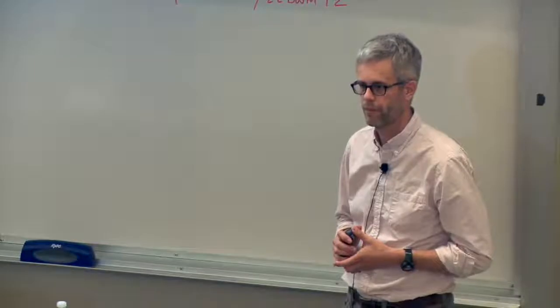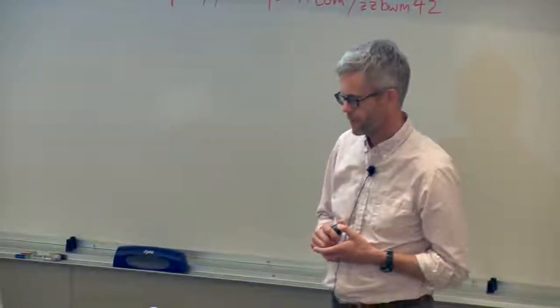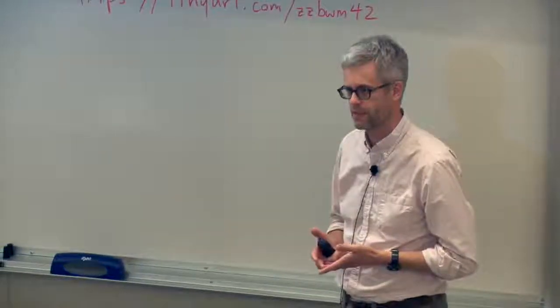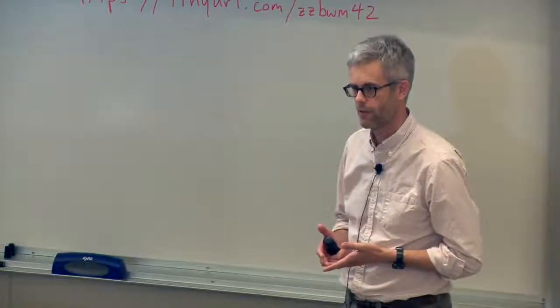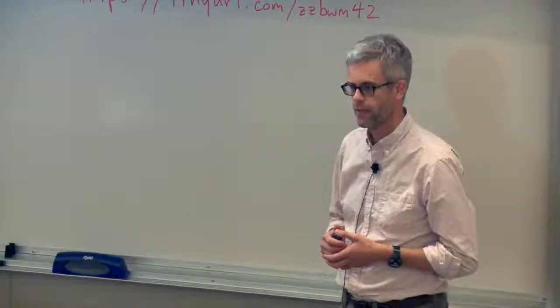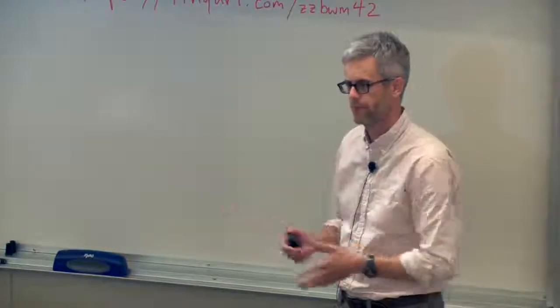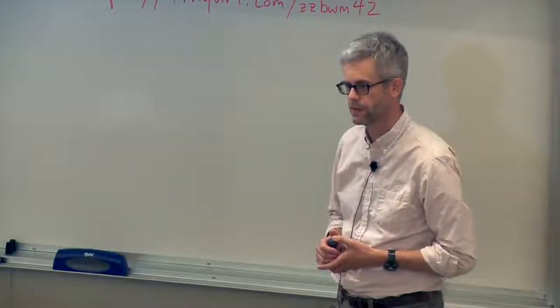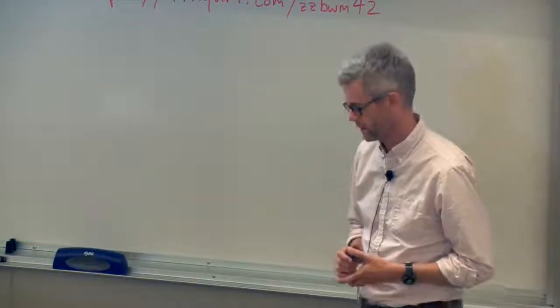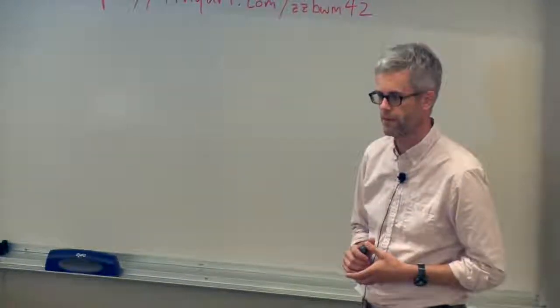What was silicon's efficiency again? Silicon right now, at 50 cents per watt, you would be getting 16% efficiency. At $1 per watt now, you could be up at 21 or 22. And we project all those efficiencies to come up by about 2 points over time. And we expect the costs to drop from like 50 to 40 cents per watt, something like that.